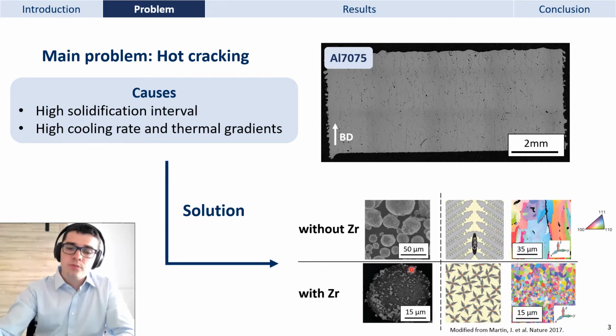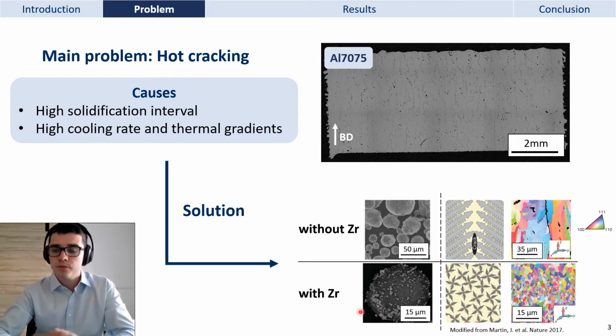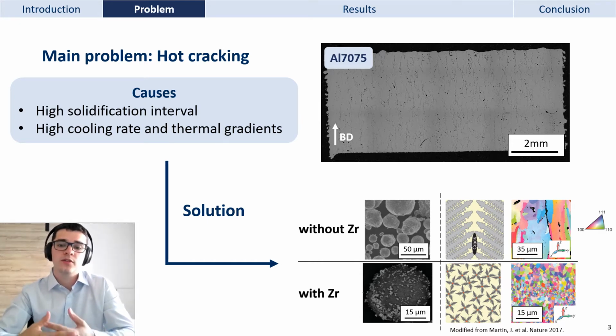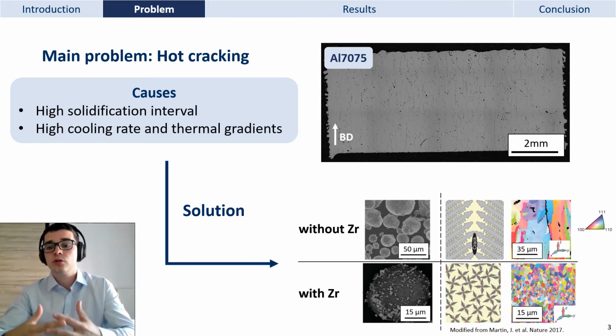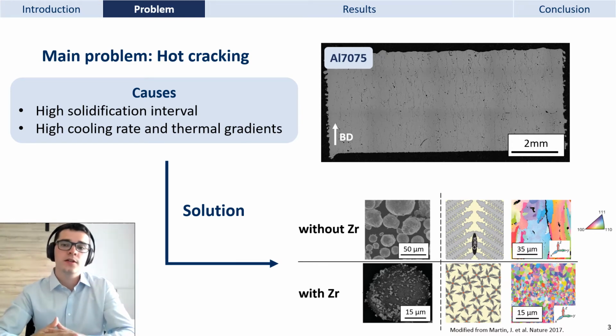When you add zirconium to the aluminum 7075 powder, the dendrites form preferentially on Al3Zr submicrometer precipitates that are formed at the beginning of the solidification. It gives a microstructure composed of fine equiaxed grains that are highly resistant to hot cracking.